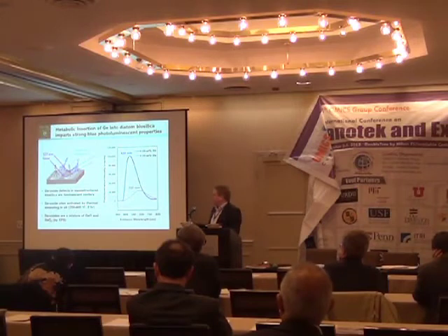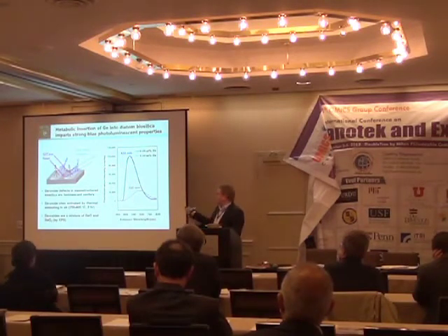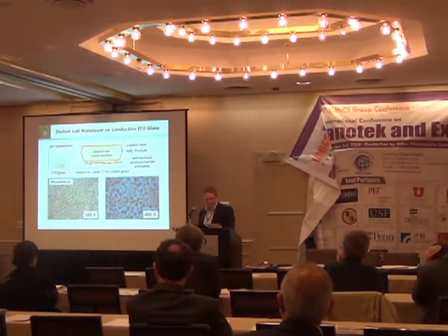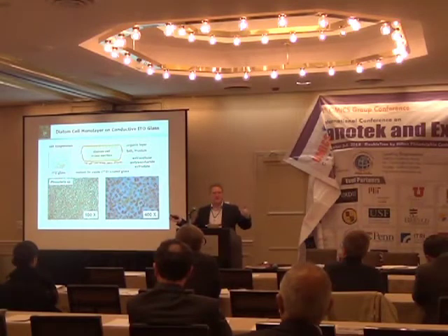When we impart these germanium oxide defects into the silica nanostructure, we greatly increase the photoluminescence emission capacity of this material, and we also shift the center luminescence into the blue range. So this gives you an illustration of how we can grow up the organism and then control the composition of foreign metal oxides into it.